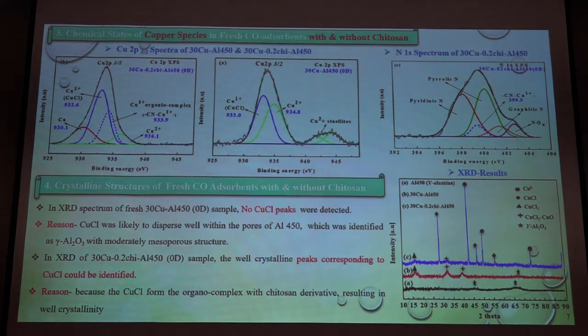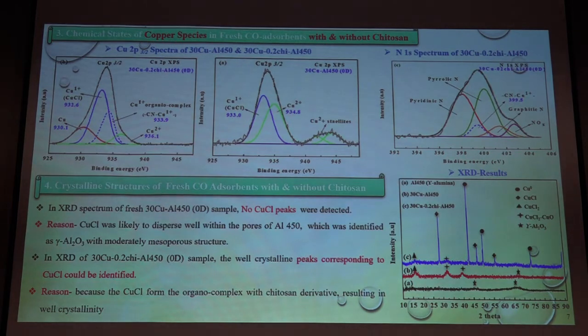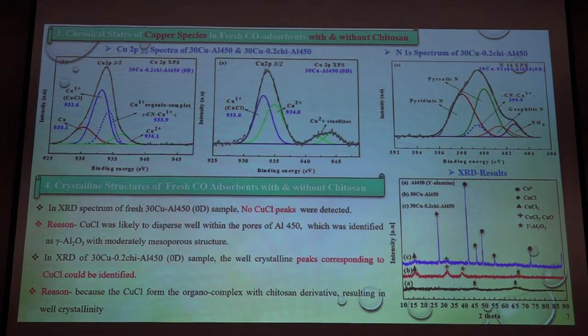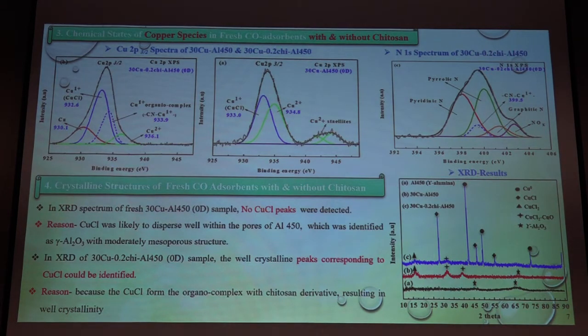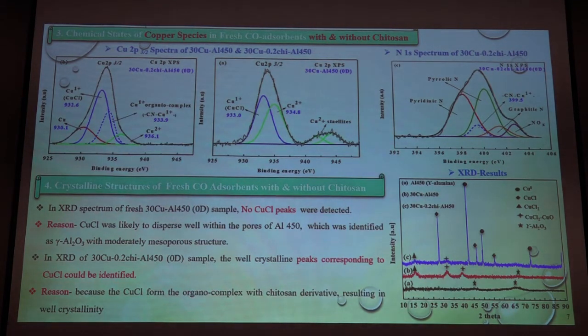In the blank sample on the right side, the doped copper 1 ion exists in its original form, like the copper 1 chloride form. But in the chitosan-modified sample, in addition to its original CuCl form, some of the copper 1 plus ion makes a complex with the nitrogen of the chitosan.